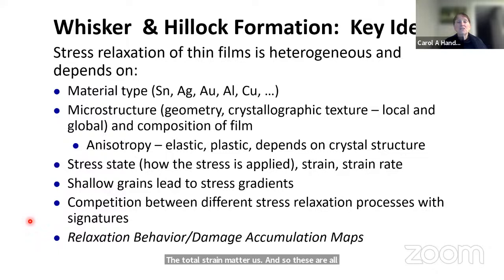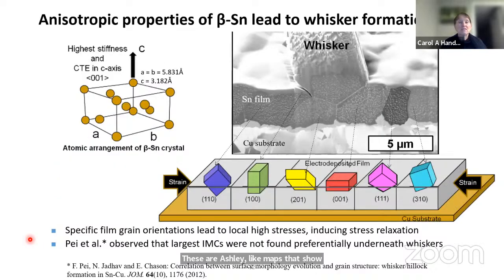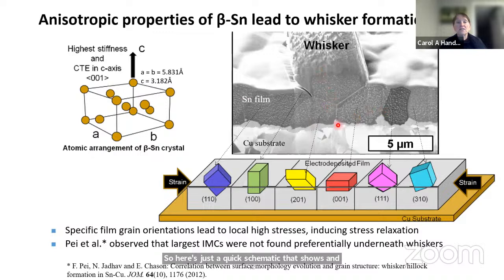Shallow grains lead to stress gradients that I'll show you in a while. And then there's a competition between different stress relaxation processes with different signatures. One of the things we're aiming to do is develop more stress relaxation behavior and damage accumulation maps. These are Ashby-like maps that show how the structures behave and how they change. So here's a quick schematic that shows an illustration of a whisker in a tin film. Each of the grains has a different orientation.